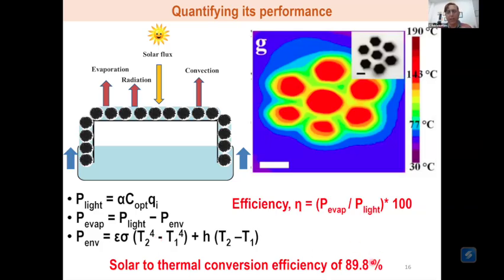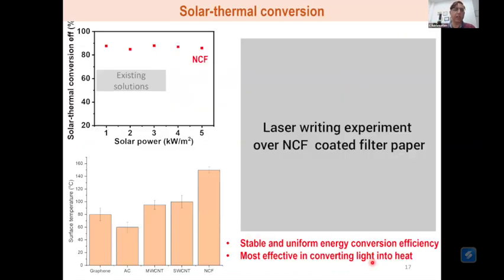This conversion of light to heat at 90% is something very unique, because like you see from the slide, the existing solutions, like, for example, the rooftop solar water heaters and other forms of titanium nitride, a lot of different materials are there, but their conversion efficiency is close to 70% at the best. This is the best case scenario. Whereas for NCF, we are already touching 90%.